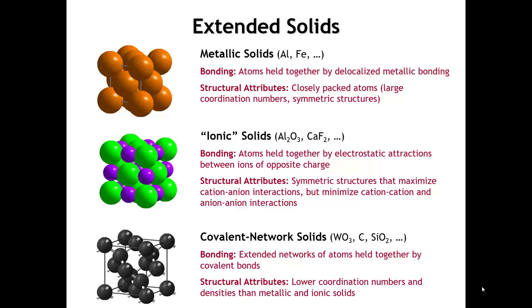Then we can also talk about solids like diamond, silicon dioxide, tungsten trioxide, where we have strong localized covalent bonds holding the atoms together. Typically there, we'll see smaller coordination numbers. Sometimes we'll see high symmetry structures, and sometimes we will see lower symmetry structures. And a lot of that has to do with the coordination preferences of the elements in the substance, as well as constraints that come from the stoichiometry, as we will see.